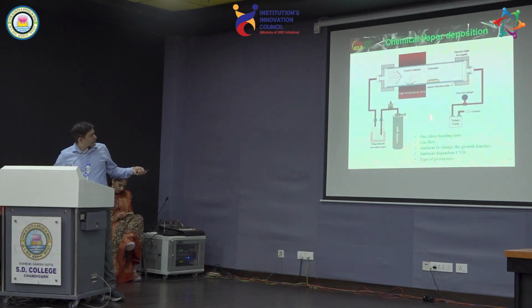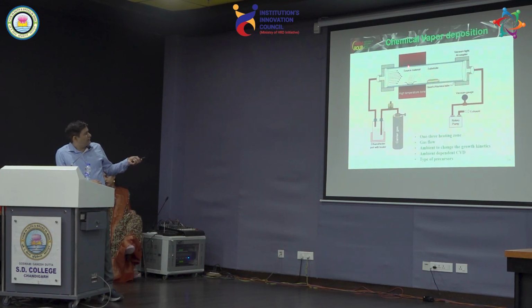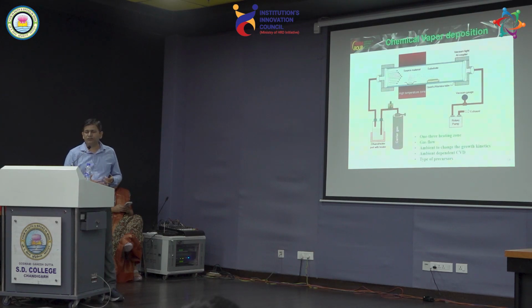Okay, so what is that? This is the schematic of the system which is used to fabricate all these 2D structures. This is chemical vapor deposition. So this is the high temperature zone, and this is the material which is a solid. Then we increase the temperature, so we are creating the vapors. Now these vapors are transported by this carrier gas, and this is the substrate which is kept at a lower temperature. So these vapors will condense on this substrate, and then we will have thin films or 2D materials growth by using this chemical vapor deposition.